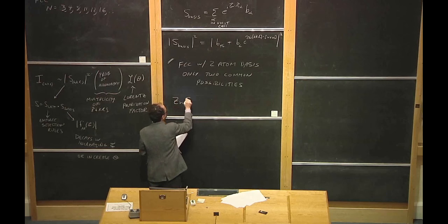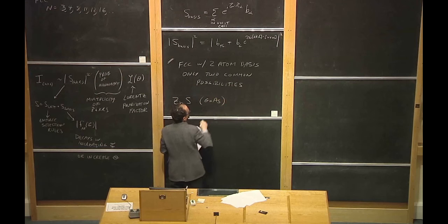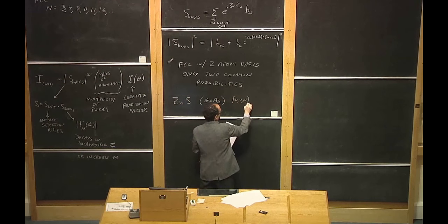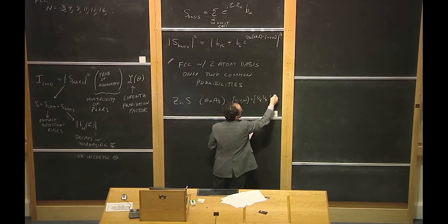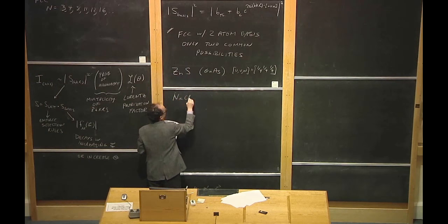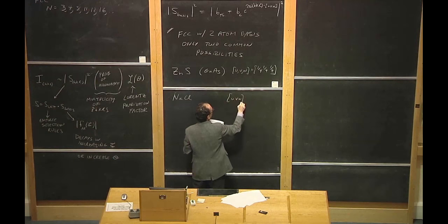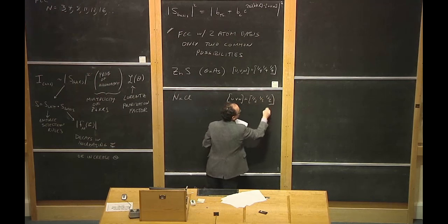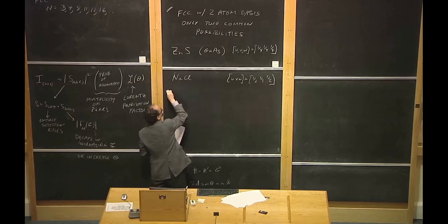There's the so-called zinc blende structure, which is the same as the gallium arsenide structure, which we talked about in class, which puts UVW at the position 1/4, 1/4, 1/4. And the other possibility we also discussed is the sodium chloride structure, which has UVW at 1/2, 1/2, 1/2. So can we figure out which one of these two possibilities it is?